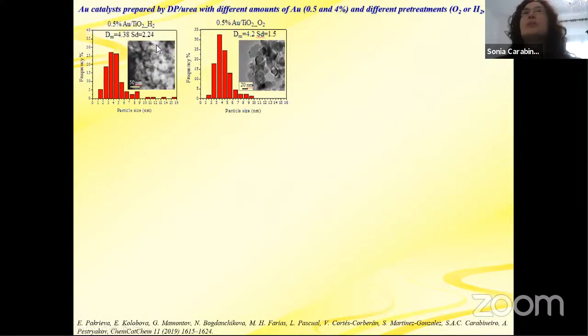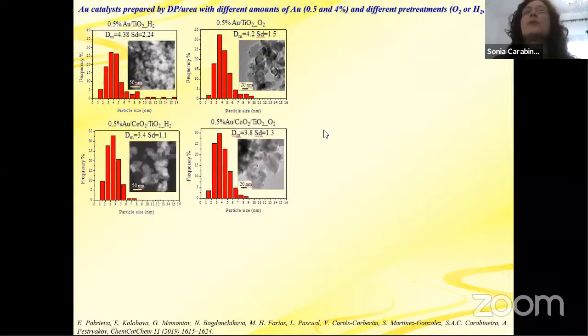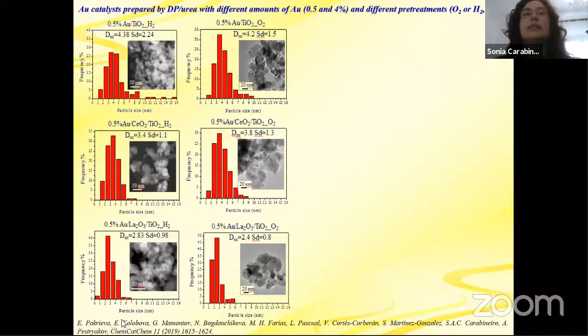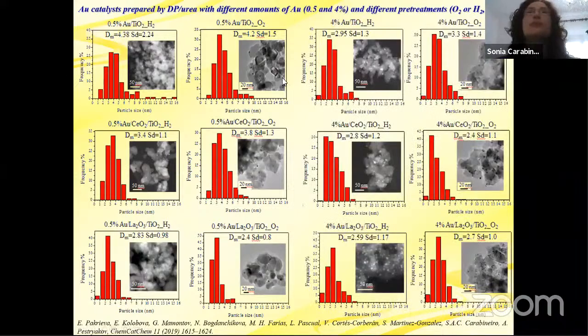And here we have some gold catalysts prepared by deposition precipitation with urea with different amounts of gold. So we have 0.5% and 4%, and different pretreatments, hydrogen or oxygen pretreatment. Here we have on titanium dioxide. Here we have on cerium titanium, so it's mixed support. Here we have lanthanum titania. All this is on hydrogen, this is on oxygen. And here exactly the same, but with 4%. So the same supports, mixed supports, and different treatments. So we have different sizes of gold nanoparticles and also different size distributions, but usually small size in all the cases.